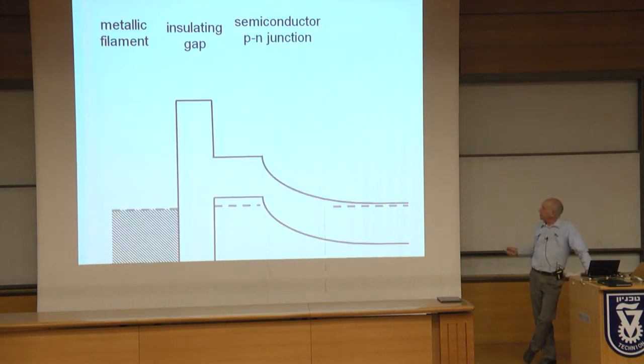Okay, this is the band diagram of the device. We can see here this is the metallic filament. We just look at it as a conventional metal at Fermi level. This is the insulating gap, a very small gap, which remains inside the oxide, about 1 nanometer, more or less. That's what we believe. This is a P-type semiconductor, and this is the N-type semiconductor, just the P-N junction. The role of the P-N junction is to separate electrons injected into the conduction band from holes injected into the valence band. So we can learn a little bit about the transport through the filament.